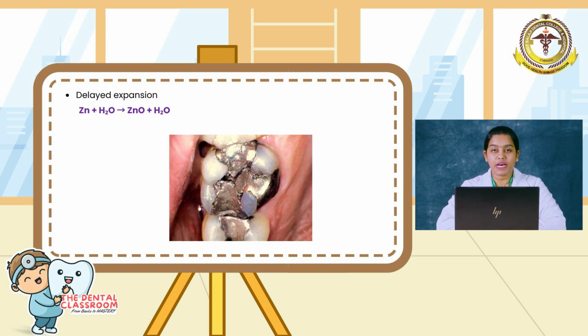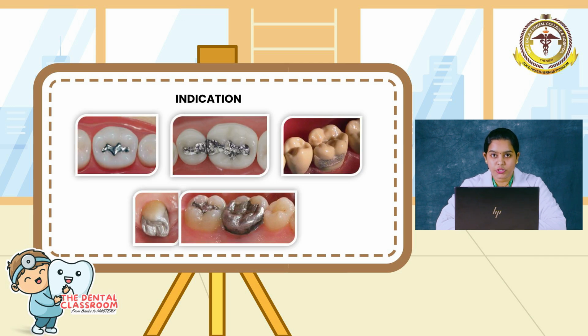Another significant drawback of silver amalgam is its tendency for delayed expansion. This occurs in zinc-containing amalgam, which upon contamination by moisture during manipulation results in formation of zinc oxide and hydrogen gas. This hydrogen gas accumulates within the amalgam, exerting enough pressure to cause the amalgam to expand. This expansion occurs 3 to 5 days after amalgam placement. This type of expansion can reach values greater than 400 micrometers.